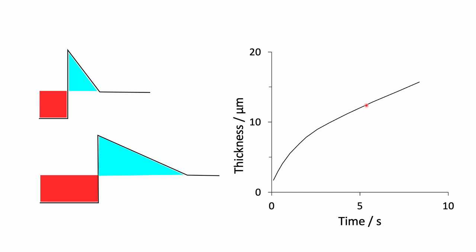So this slowing down is entirely because the average composition of the liquid is changing as the alpha forms and solute is partitioned into the liquid to a greater and greater extent as the alpha becomes bigger. And this is why this is not at all like the eutectic reaction, where the average composition of the liquid does not change.